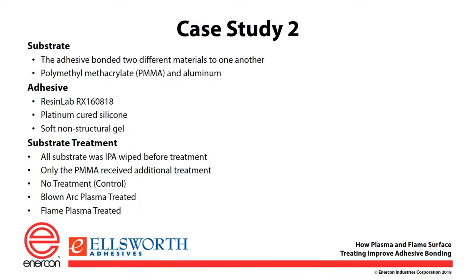A second case study involved the use of polymethyl methacrylate being bonded to aluminum. So here we have two different substrates being bonded that have different coefficients of thermal expansion. The adhesive that was used is Resin Lab RX 160818. This was a platinum cured silicone. This is a soft non-structural gel. So this is not intended to be a structural adhesive.